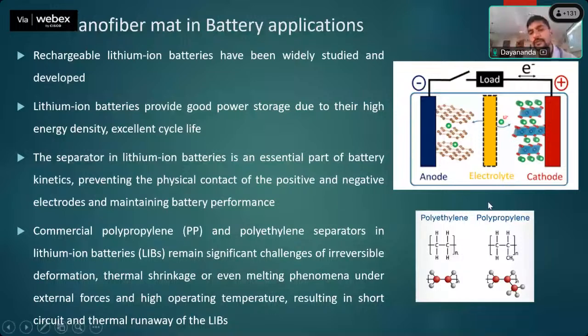To avoid that, the anode and cathode can also be modified. The surface of the anode material should be coated using electrospinning technique, so that you get large surface area and effective doping of lithium ions during charging and discharging, increasing efficiency. At the same time, you can also play with the electrolyte and modify it.